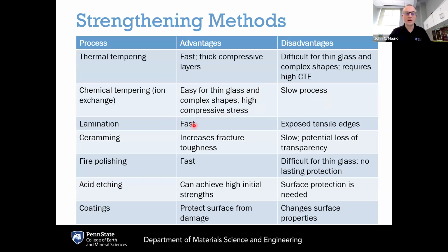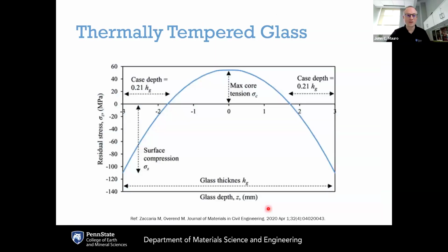Lamination can also be used. Ceramming is another pathway where you could turn the glass into glass ceramic to increase the fracture toughness, but you can compromise some of the optical properties that way. Fire polishing is a fast way to help reduce the severity of flaws on the surface, but it doesn't provide any additional lasting protection after that. Likewise, acid etching can reduce the severity of flaws, at least initially, but there's no protection later on. Coatings can also be used to provide longer-term protection, but that could also compromise some of the surface properties and the optical properties of the material.